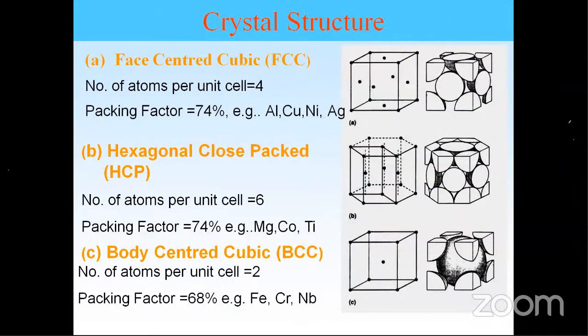Then we have, this you have also studied mostly, but I just want to refresh it, because for every application, the selection of material with respect to crystal structure is very, very important. And in general, I'll tell you, FCC materials can be used at low temperature as well as high temperature, and ambient temperature also. Take the case of steel, all austenitic steels are FCC, and they can be used at all temperatures, high temperature, ambient temperature, as well as low. Of course, nickel alloys fall in FCC, so they can be used at low temperature also. But normally at ambient temperature they are not used, because normally they are highly alloyed, so it will be costly.